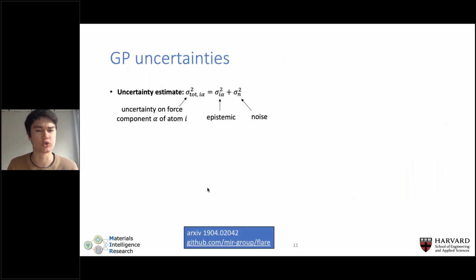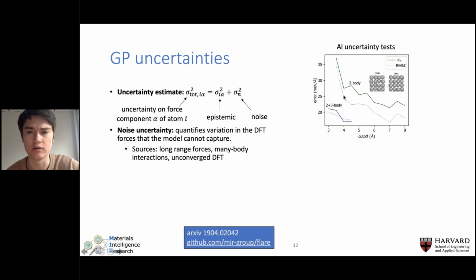And so I'd like to drill down a little bit more and say a bit more about what these uncertainties mean in the context of atomistic simulation. So to show you one simple example of fitting an aluminum force field, here on the x-axis, I'm sweeping the cutoff radius of the atomic environment. So this is controlling the degree of locality of the model. And as we increase the cutoff, we're including more and more atoms inside of the cutoff sphere. And the dotted line here is the true error. So it's the difference between our ab initio values and the predictions of the model. And you can see, this is the typical picture that you see. As you increase the cutoff, the error goes down up to a certain point, and you eventually converge the error. So at a certain point, expanding the radius doesn't really allow you to improve the error very much.